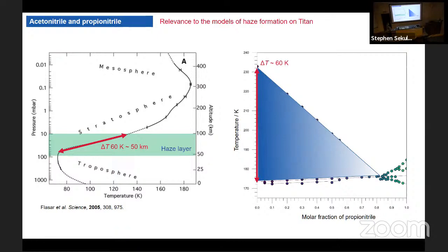Look at the phase diagram. If you take a look only at acetonitrile, which is not mixed with propionitrile, it will crystallize around here. But look, if you mix it with propionitrile, the lowest point of crystallization will be the eutectic point. And that eutectic point is around 60 Kelvin lower than the crystallization of pure acetonitrile. That means that if we have it mixed, this difference of 60 Kelvin may translate to 50 kilometers difference in